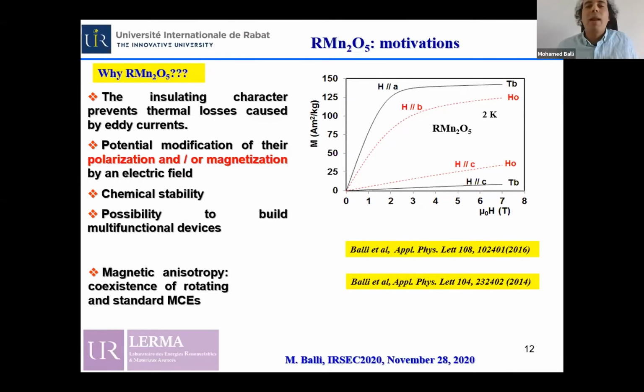This will enable us to prevent thermal losses caused by eddy currents between magnetizing and demagnetizing these materials in magnetic refrigeration systems. Also, the strong coupling between magnetic and electrical ordering parameters in this compound will enable us, for example, to control the magnetization